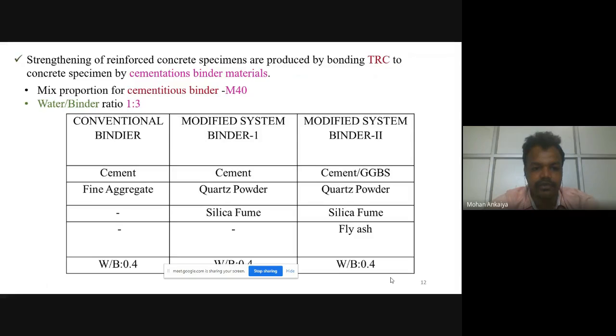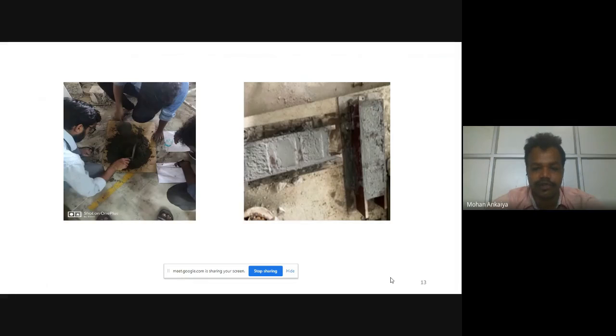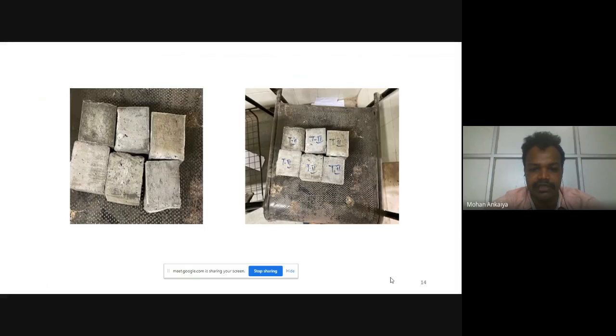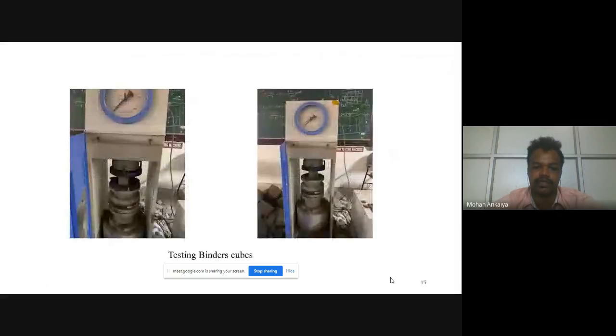These are the casting photos. As per IS, we cast 3 sets of cubes for 7 and 28 days. The cube size is 70.6 by 70.6 mm. These cubes are tested only for compression due to the COVID pandemic. We cannot concentrate more on this, but the work is going on further.